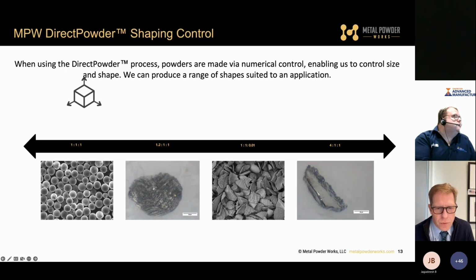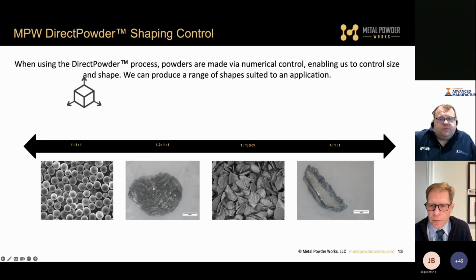Typically, we have been producing what you see here, what we call equiaxed particles, a little bit prismatic, but we've also produced platelets and some high aspect ratio material along the way. If you take the product and run it through a spheroidizer, you also get nice round particles. So that's also a potential output of our process.